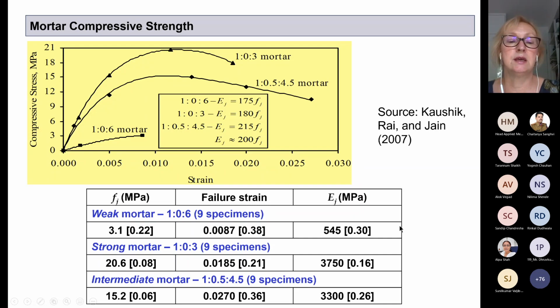So you can see here in the table for this weak mortar, which is 1:6, that the average strength was 3.1 megapascals. Failure strain is 0.0087. That is not dimensional. This is modulus of elasticity. We're not that interested in the modulus of elasticity of mortar.